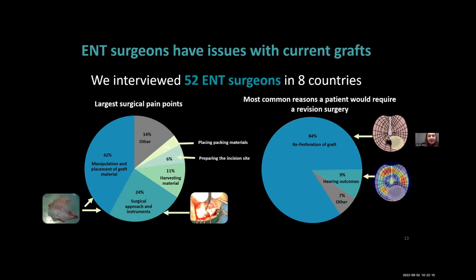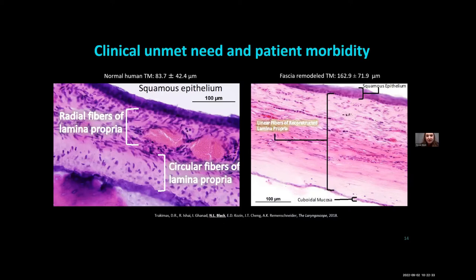And then we also asked them common reasons why a patient would require revision surgery. So as we talked about earlier, healing outcomes not being ideal, so the graft reperforating, but then a number of patients also undergo revision surgeries just due to poor hearing outcomes as well. And so the reason for these poor hearing outcomes, as I mentioned, is likely because these grafts do not degrade or remodel. And so the normal human eardrum, here's a cross section showing, it's about 80 microns in thickness. And you can see very clearly these two layers of the lamina propria of those radial and circular collagen fibers that I talked about.